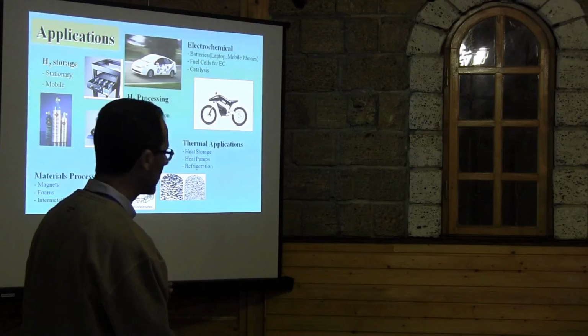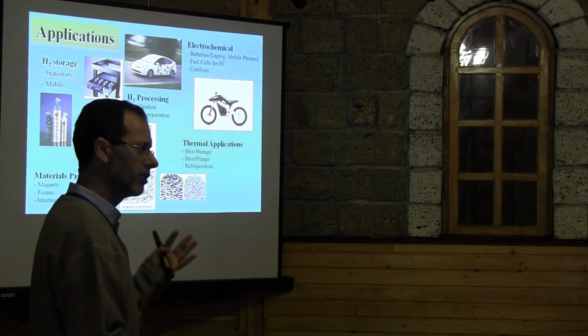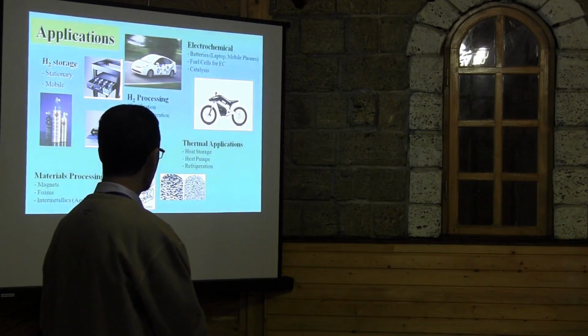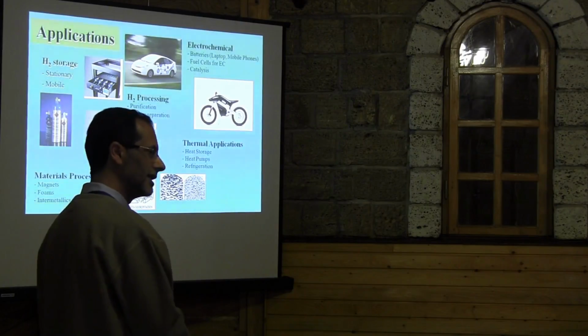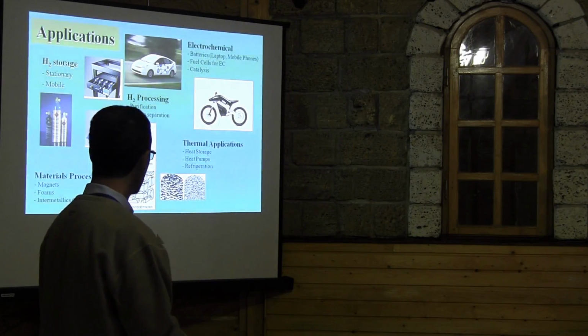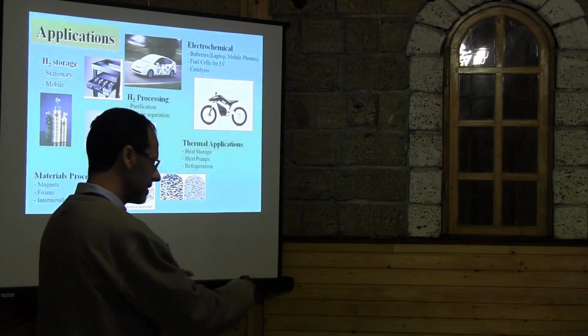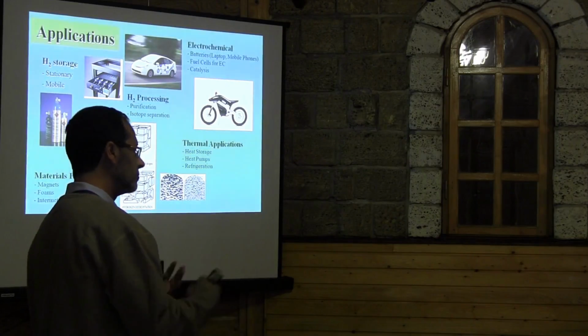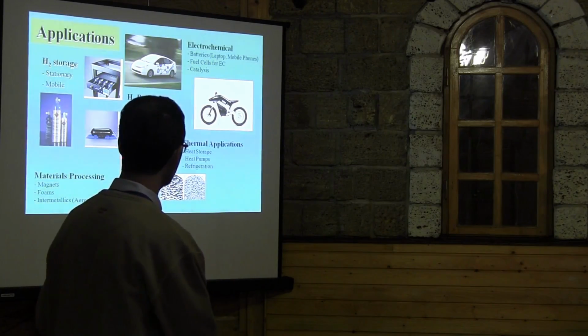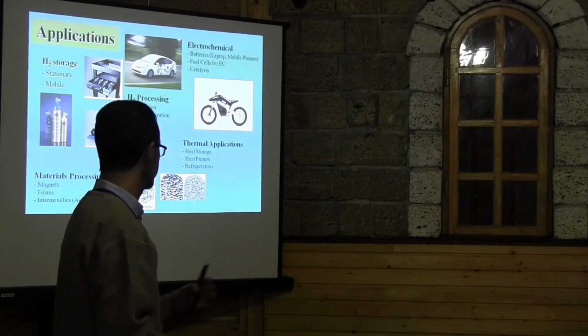So when this bulk interacts with hydrogen, this is neodymium-2 iron 14 boron, one known hard magnetic material. When you interact with hydrogen, it decomposes into neodymium hydride, iron and boron, in small particles. But when you remove hydrogen again, it becomes a new material with improved magnetic properties.